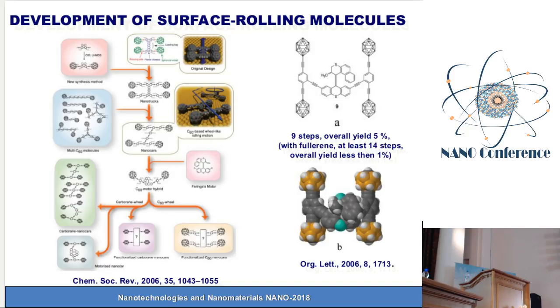It's about nanodevices. The first nanocars, the molecules able to move on the surface, were built of fullerenes. But the chemistry of fullerenes is not easy, and synthesis of this kind of structure took 14 steps, and the overall yield was only 1%. It was soon realized that boron clusters, like for example paracarborane shown here, are more convenient because the chemistry of boron clusters was at that time much better developed. So this kind of molecular car, nanocar, was synthesized in 2006.